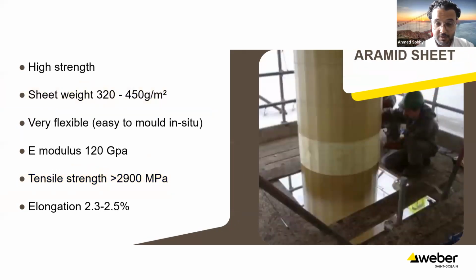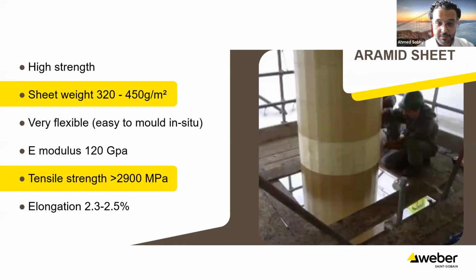Moving on lastly to the Aramid, again, not too dissimilar from the previous families. The sheet weight is about 320 to 450 grams per square meter. Tensile strength is 2,900 megapascals. Elongation is about 2.3 to 2.5% at rupture.